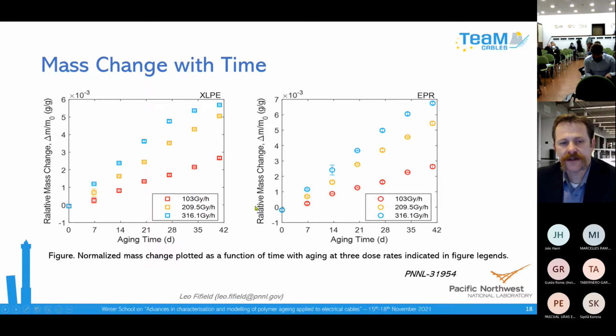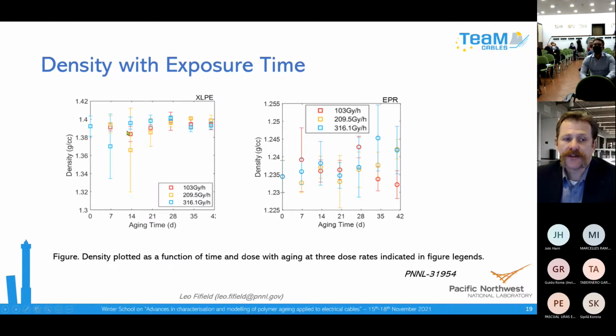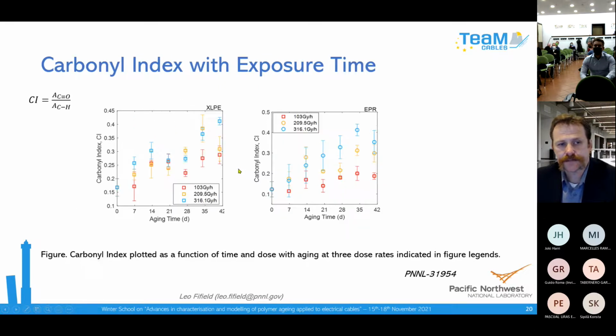So we measured these materials in several different ways. We looked at the change in mass of the materials, which also tracked closely with dose. We measured the density of the materials, and it was a surprise to me that we did not observe change over the parameters explored, which were up to over 30 megarads, 300 kilogray. We didn't observe any trend in change in density at all for these materials. I was kind of surprised by that. I thought that we would, but we didn't see that.